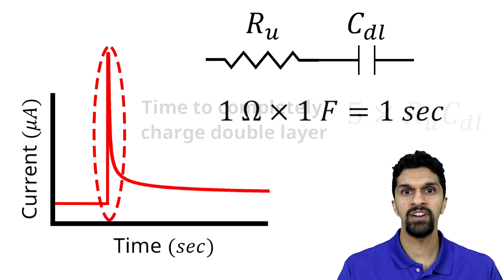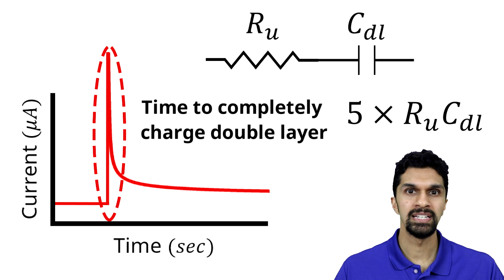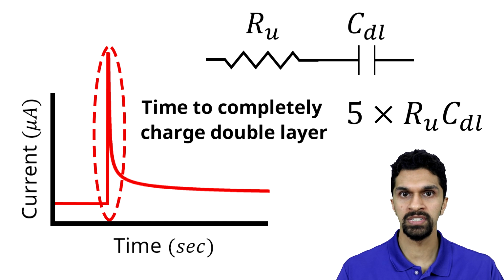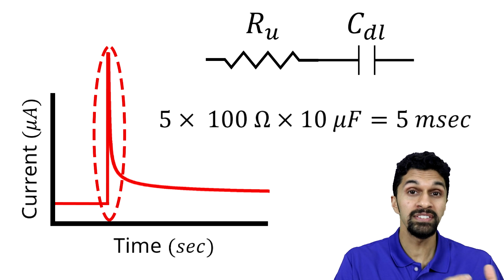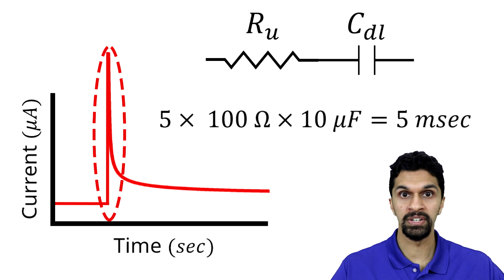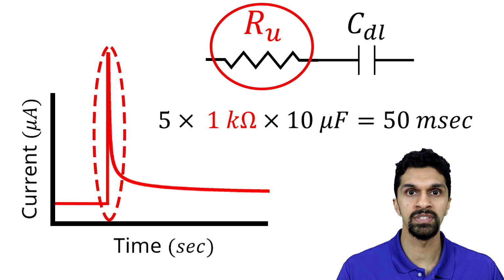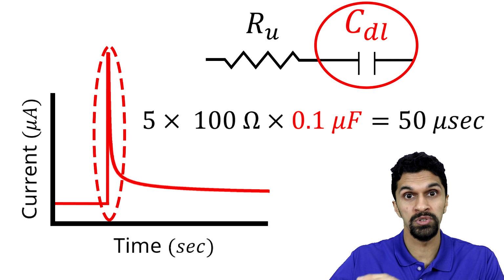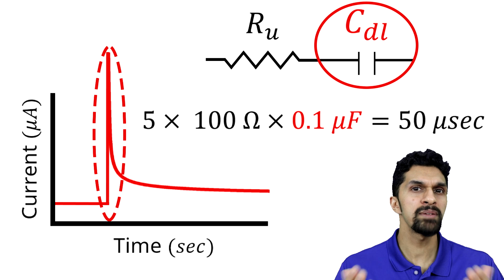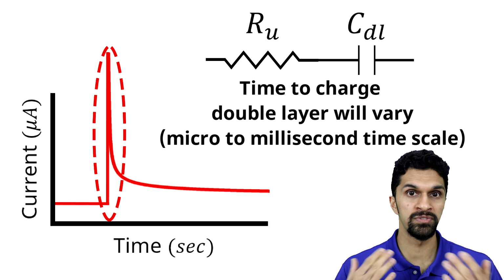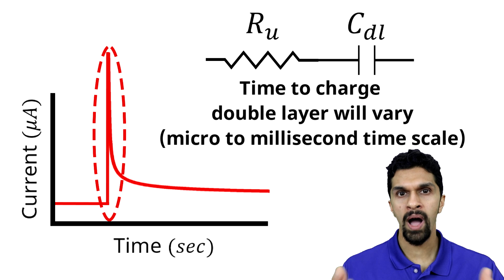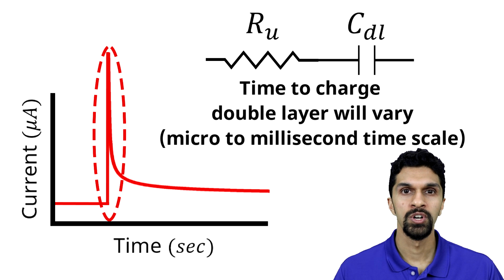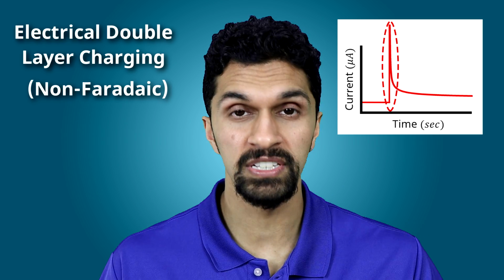And specifically, 5 times RC, or 5 RC, is the time it takes to charge the electrical double layer. So depending on your electrochemical system, maybe you have a large uncompensated solution resistance, or you have a small area electrode, so you have a low capacitance, the time it takes to charge the electrical double layer will vary. But in general, for a wide array of different electrochemical systems, we're looking at the charging of the electrical double layer on the microseconds to milliseconds timescale. So part of this large spike in current is associated with the charging of the electrical double layer.